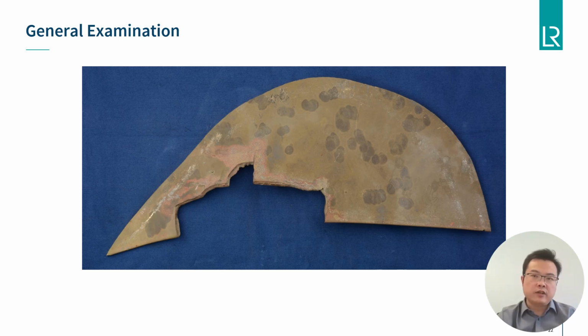Similar to other failure investigations, for this one we started with the visual examination of the section from the pressure side of the propeller. The blade has apparently suffered mild corrosion and discoloring, which is normal for a propeller blade in seawater. We usually use a type of nickel aluminum bronze, which is very likely the case here as well. But interestingly, you can see some contrast of localized granular areas, which indicates there has potentially been some welding taking place on the pressure side of the blade. The welding is in various positions and consists of both small isolated spot welds as well as very large continuous welds.